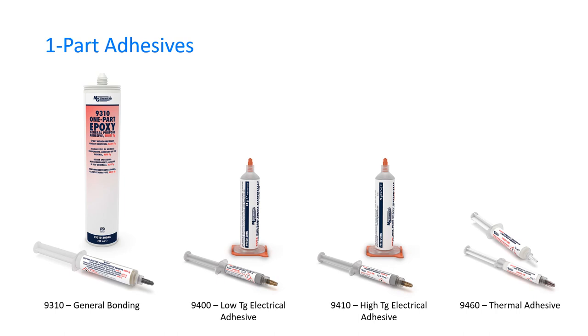We look at the different packaging sizes available for the one parts. We start with the 9310. I already introduced that way back at the beginning of this webinar, but just to circle back, the 9310 is a general bonding one part epoxy adhesive. We have two electrically conductive one part adhesives, the 9400, and that's the lower glass transition. The lower glass transition is indicative also of the lower minimum cure temperature. So the 9400 requires temperatures of 70 degrees or higher to initiate cure, whereas the 9410 is a higher Tg compound. So again, it's more stable at higher temperatures, whereas a lower Tg is more ideal if you're dealing with something that requires a lot of thermal cycling.